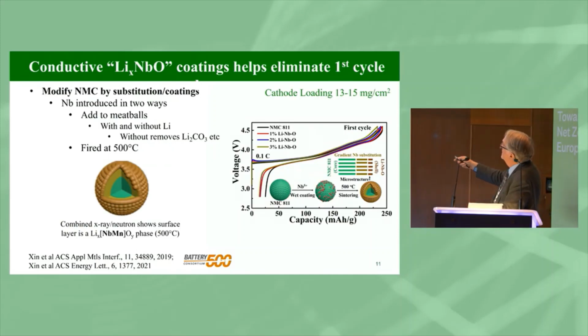So what effect does this have? If we do low temperature, 500 degrees centigrade, here's our original meatball. You can now see we've got a coating on the outside and the niobium diffuses into the top few layers. But what we found out by doing a joint X-ray neutron study is it's much more complicated than that. The surface coating is in fact a mixed niobium manganese phase. So the niobium goes in the first few layers, kicks out the manganese that goes into that surface coating.